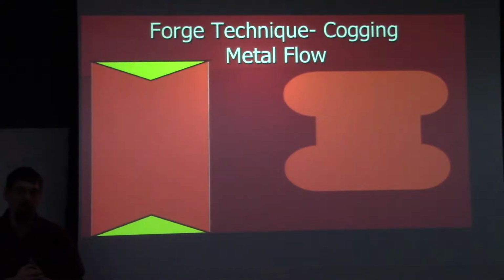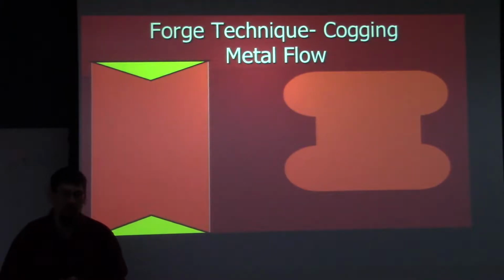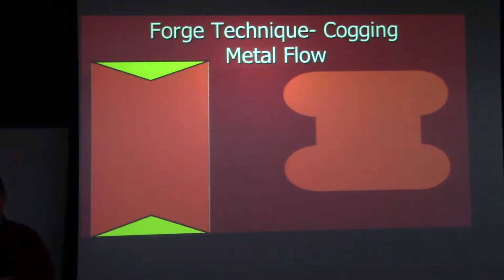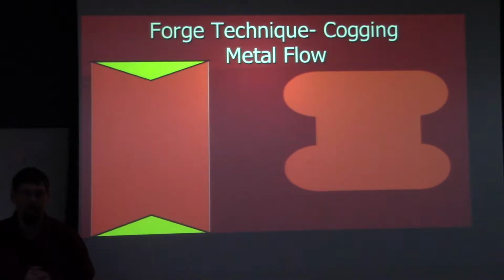You might remember I put a slide up that showed the relationship between hammers and presses in the very first lecture. And I said that from an industrial standpoint, doing this kind of open die type of work, you need a hammer of about 50 pounds falling weight for every 1 square inch of cross section that you're dealing with. And then there was a slide that related hammer size to press size, and I think it was something like an 80,000 pound falling weight hammer was equal to around a 2,000 or 3,000 ton press. So what you're seeing is that you have to get some truly enormous hammers to begin to have something comparable to the kind of presses that are used even on what would be considered sort of medium size in the open die forging industry.